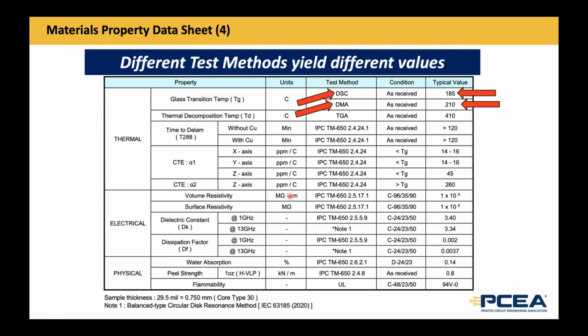One of the other things that I think people misunderstand is that a lot of times the value of one of these data points is influenced by the test method. And as you can see, the two test methods that we call out on this data sheet for glass transition temperature actually are quite a bit different. I could talk for hours about why, but if you don't know which of those test methods has been used and somebody says, well, the Tg is X, whatever X is, 200, 150, you have to know the test method. If you don't know the test method and you try to compare to another product with a different test method, you will not make a good comparison. Next slide.